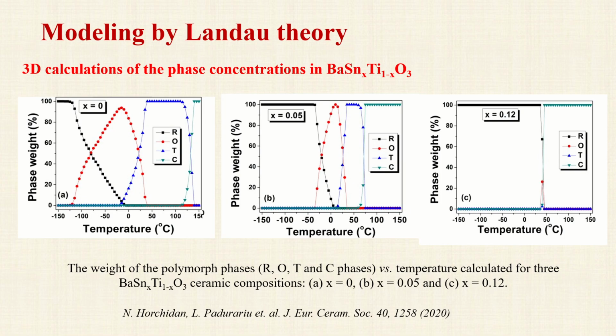The phase concentrations were computed for three systems: pure undoped barium titanate, tin-doped barium titanate with 5%, and tin-doped barium titanate with 12%. The first graph showed that even undoped barium titanate is characterized by a large temperature range of phase coexistence, around what are considered by many as transition points. According to this graph, the orthorhombic and tetragonal phases coexist from minus 10 degrees Celsius to 30 degrees Celsius.